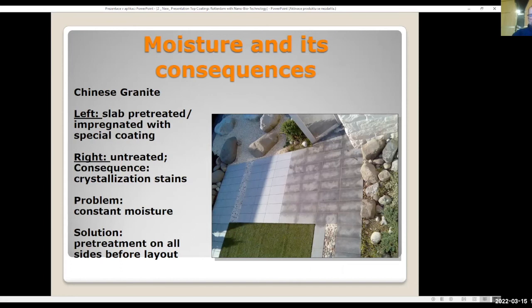Can you apply such a coating on this surface or other surfaces? You mentioned something in the beginning. It's good to do it before it's put into use. Can you do it also after? No, this one not, because you need to take it away, and you have only one chance, before the laying. Before the laying, okay. The glass, you can install and coat after. I propose it on the finished facade. Not to play with one window on the ground, but finish, and then a group of technicians comes and makes the coating.